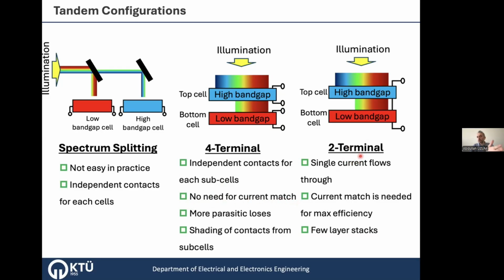And you can also have a 3-terminal structure, but I show here a 2-terminal. For the 2-terminal structure, you have 2 contacts. One is from the high band gap solar cell, and the other one from the low band gap solar cell. So you have 2 contacts, and that means you have these 2 cells serially connected, right? That means you can add the voltage of the 2 solar cells, but there will be a single current flowing. That's why if one of these solar cells has the lowest current, that will be the current you have in the circuit. That's why we say that current matching is important for 2-terminal tandem solar cells.